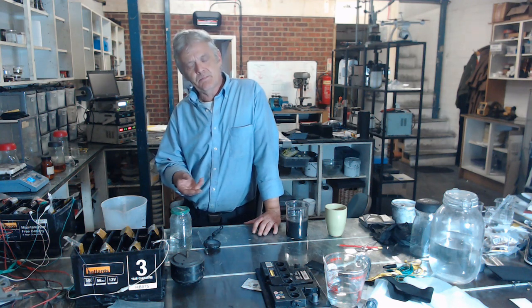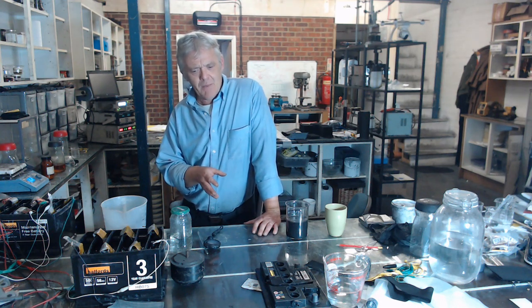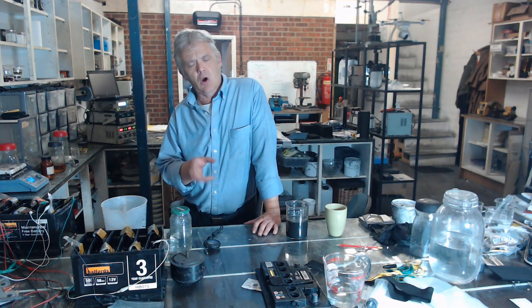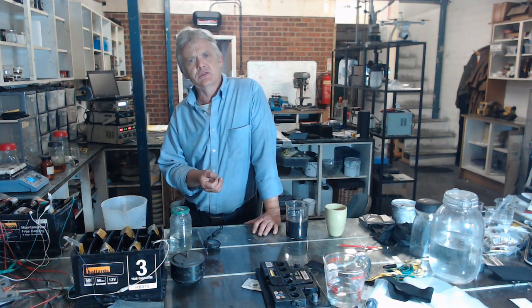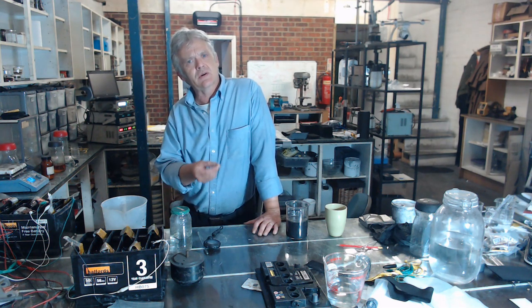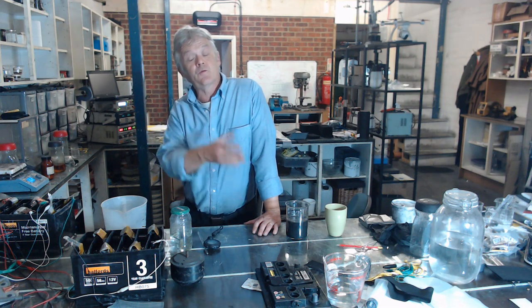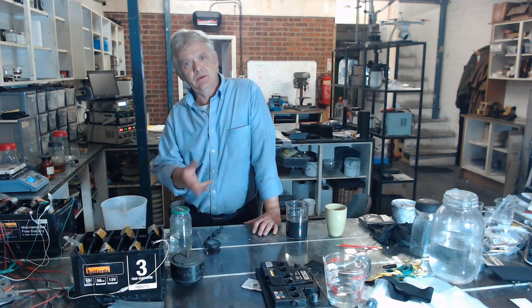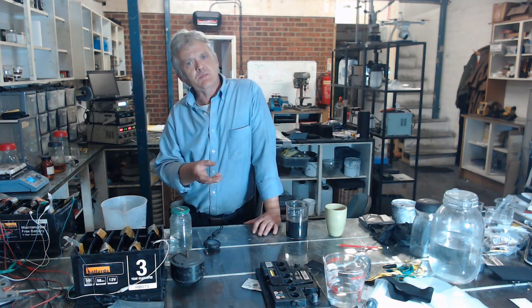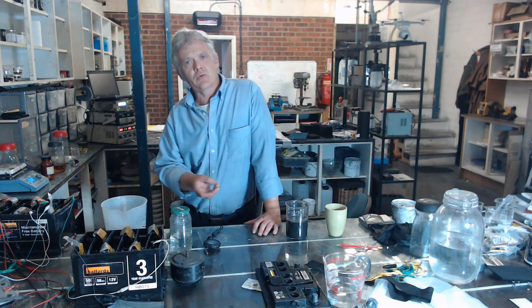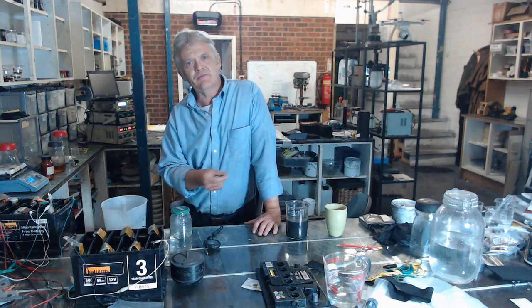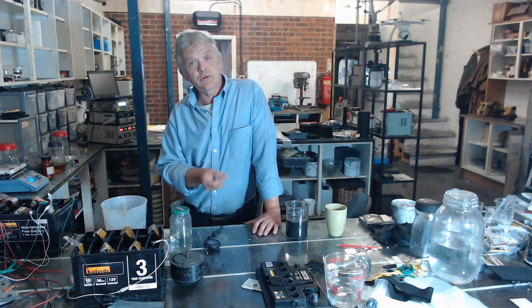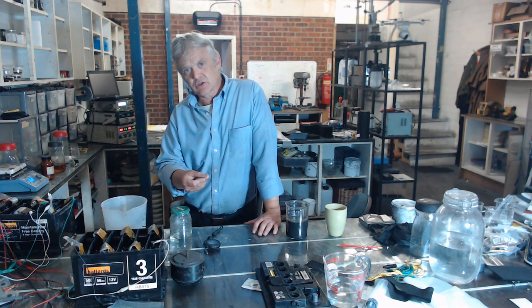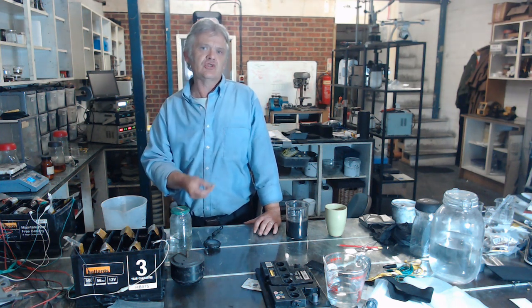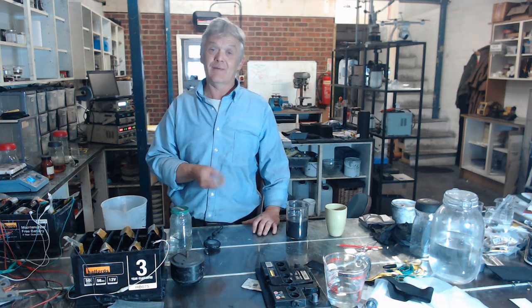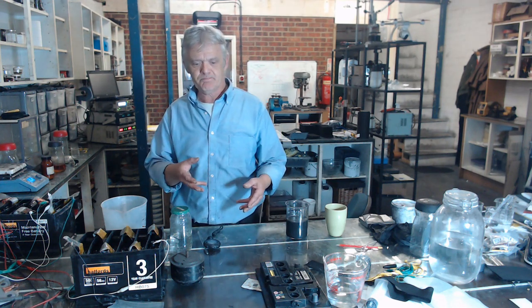And normally when they're mining flake graphite, what they do is take the rock and crush it to what's called the liberation size. That is the size at which the graphite flakes will just fall out and be free of the rock and no longer locked in. That's quite a critical size, because if you overcrush it, what you do is distort the graphite flakes and you smear them over everything else. And of course you crush those quite small, so in the later separation stages it's actually quite hard to separate them because the smeared minerals now act like the graphite, so it becomes much harder.